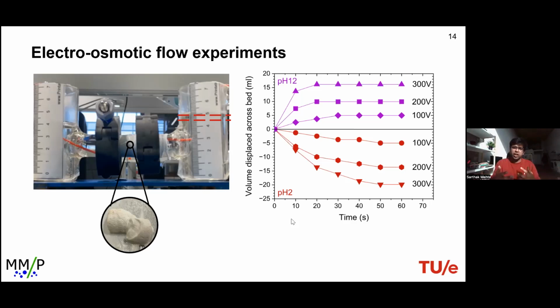Because of the change in silica particle polarity, we see that the flow is in different directions. The aqueous diffusive region has different charges, and therefore one moves towards the positive electrode, the other moves towards the negative electrode, and we can see a difference in the direction of flow.